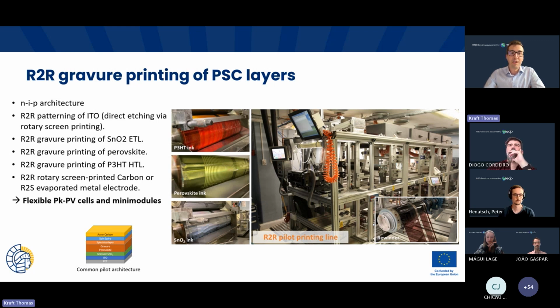This is followed by, of course, annealing, and then gravure printing the hole transport layer, which is a very good workhorse for us, is the P3HT, poly-3-hexylthiophene, which if any of you know organic photovoltaics, you might be familiar with. And then we'll print, with rotary screen print, the back carbon electrode.